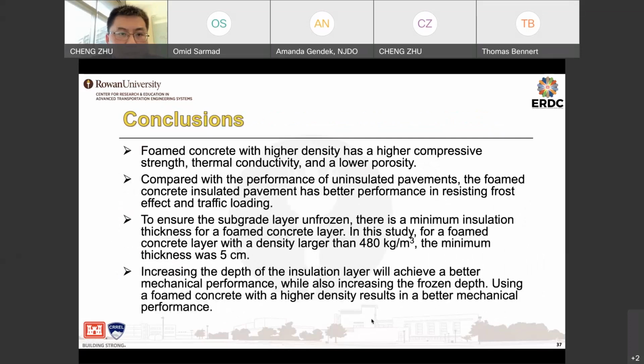So in conclusion, in this study, we looked at foam concrete with different densities, and we constructed this full soil box or pavement structure to test the effect of this insulation layer on temperature change under different conditions. Some of the conclusions we have are that the foam concrete insulation pavement has better performance in resisting frost effect and traffic loading. And to ensure the subgrade layer stays unfrozen, there is a minimal insulation thickness for the foam concrete layer. Based on our materials, these are the values we get.